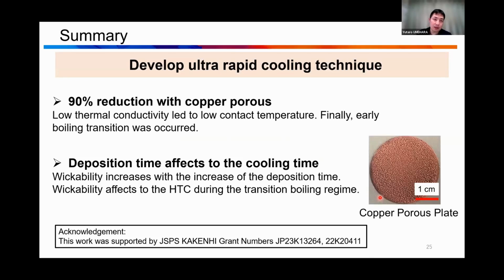So this is a summary. When we apply the copper porous to reduce the quenching time, the sprayed copper can achieve a 90% reduction of quenching time, because the low thermal conductivity leads to a low contact temperature. And finally we can get an early boiling transition. Also, the deposition time affects the cooling time, because maybe wickability has some effect on reducing cooling time.